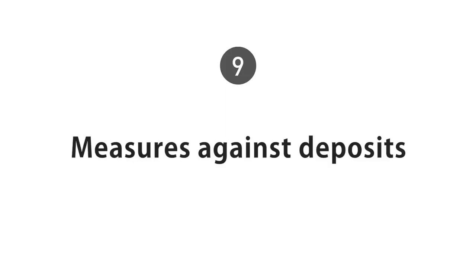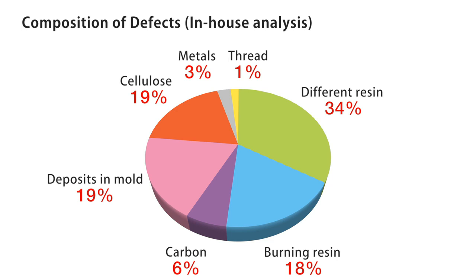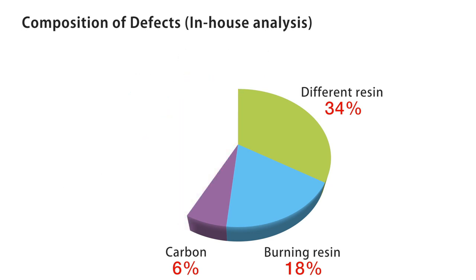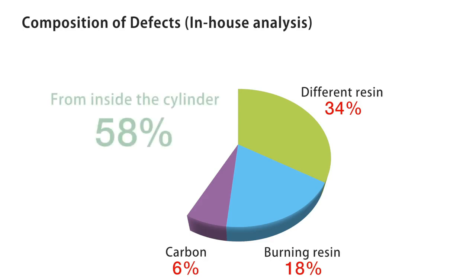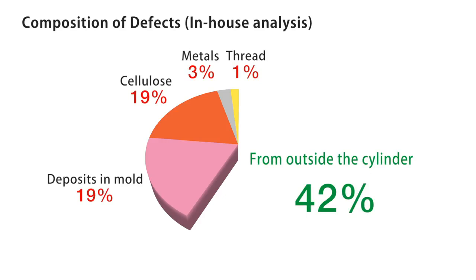Over the 20 years of ASACLEAN's history, many customers have requested consultations on failures caused by deposits and contaminants. We have investigated and analyzed such issues. This graph summarizes the causative substances for failures caused by deposits and contaminants. Occurrences from inside the cylinder account for 58% of all failures, such as the burning of the same or different resins and introduction of carbon. The remaining 42% are due to the ambient surroundings, including stains on the mold and the introduction of cellulose, such as paper bags for resins.